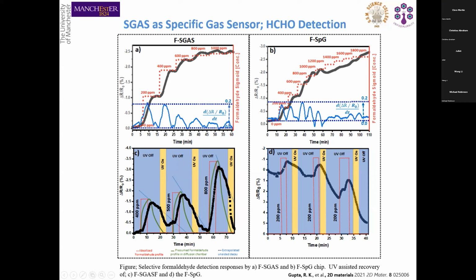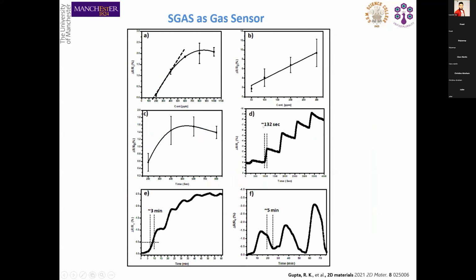And on the other side, the recovery of a supported graphene is not as good as the recovery of your suspended arrays, because when you eliminate the light, whatever is under the graphene and the oxide will get permanently charged up, and it will not give you a full recovery. Rather, it will dope the graphene on the other side. So that's why we do not use it. This just shows that the graphene sensor with the suspended structure is much, much better than the graphene sensor with the supported structure.